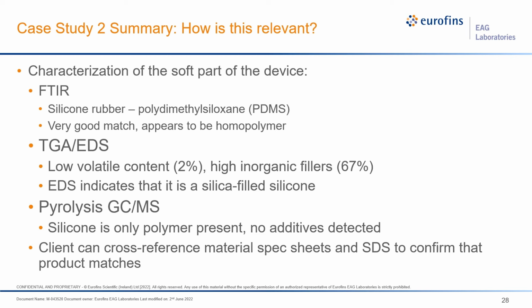Finally, with the pyrolysis and GCMS, we didn't detect any prominent additives in our desorption step, and the silicone is really the only species that's present here. So now the client can take this information, cross-reference their other materials and safety data sheets to confirm that the product matches their expectations.